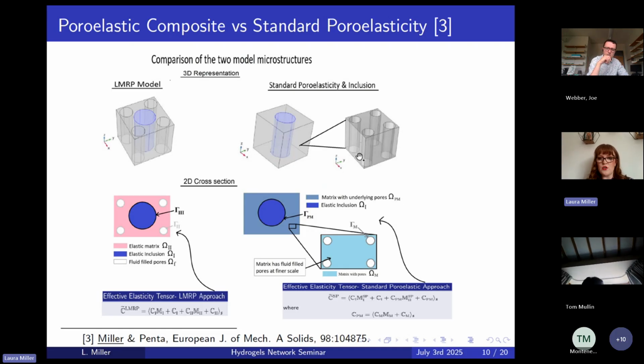Here, as I mentioned, was the best possible case we could come up with using what was in the literature. And that means we had a two-step process. What we had to first of all do was solve a typical porous matrix problem and use that then as an input parameter for our composite problem.